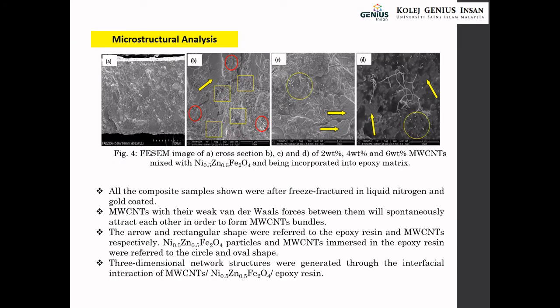So this is the microstructure analysis, and we are taking it for the cross-section part. All the composite samples shown were after freeze fracture in liquid nitrogen and gold coated. MWCNTs, with their weak van der Waals forces between them, will spontaneously attract each other to form MWCNT bundles. The arrow and rectangular shape refer to the epoxy resin and MWCNT respectively. Nickel zinc ferrite particles and MWCNT immersed in the epoxy resin are referred to by the circle and oval shape. We try to produce this because we can get three-dimensional network structures generated through the interfacial interaction of MWCNTs, nickel zinc ferrite, and epoxy resin.